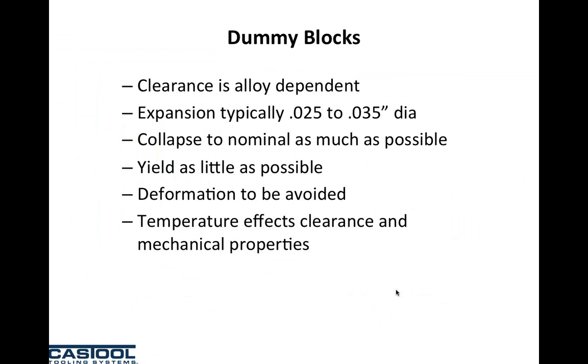Typical expansion on a dummy block is 25 to 35 thousandths on diameter. What we want to do is have the dummy block collapse back to as close to nominal as possible after the push. So when the dummy block comes back through the liner bore, we want it to go back to nominal size. We want the dummy block to yield as little as possible. All dummy blocks yield, so we're going to get somewhere 3 to 5 thou per on diameter yield of a dummy block just about immediately. What we would hope to do is to curtail or stop any further yielding as long as possible.